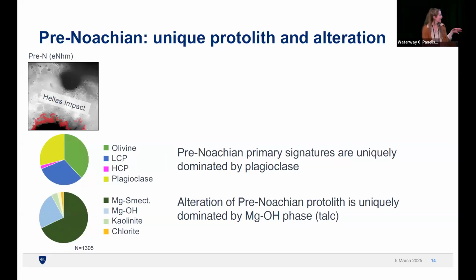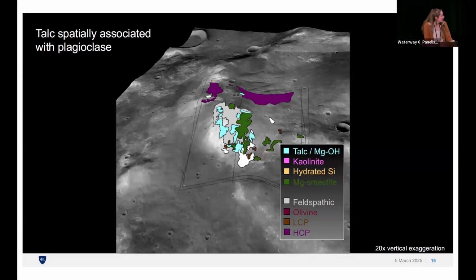So the take home here is that in the pre-Noachian, the primary signatures are uniquely dominated by plagioclase, and the alteration signature is uniquely dominated by this MgOH phase, which I won't show here, but we've shown to be comparable to talc. And this is what it looks like if you zoom into one of these massifs along the northern rim and you map in the mineralogy from CRISM. You can see that there's a distinct spatial association between many of these, but this is our highlight one, of the feldspathic and anorthositic, plagioclase-bearing lithology shown in white here, and a surrounding talc or MgOH phase shown in cyan. And we see this commonality, and sometimes we even see in the spectra the signature for plag and talc together.